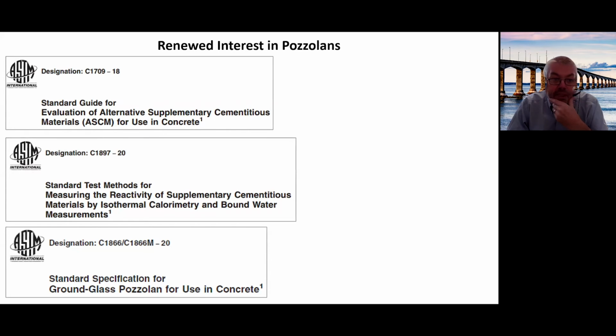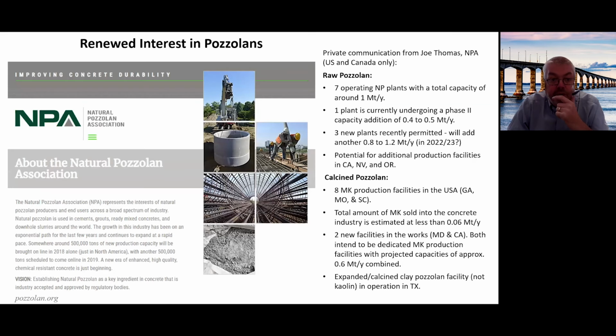So ASTM's activity included in 2018 the publication of a guide for evaluating alternative supplementary cementing materials. In 2020, these two ASTM tests for measuring chemical reactivity by isothermal calorimetry and bound water. And also in 2020, we saw a specification for what's considered to be a new pozzolan in North America, and that's the ground glass pozzolan.